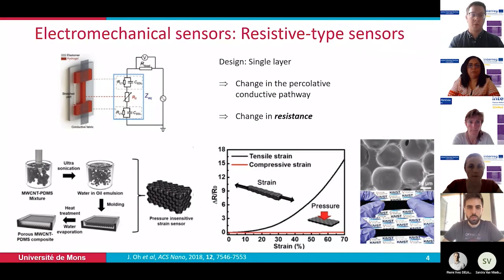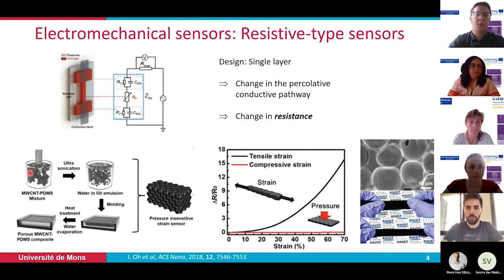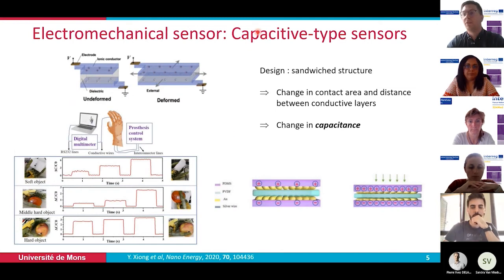As an example, we have here multiwall carbon nanotubes mixed with PDMS, and when you apply a pull on the material, you have a difference in resistance, but the constraint is that when you apply a pressure on this material, you have no response at all. A second type of electromechanical sensor is the capacitive type sensor. There you have a sandwich structure where a dielectric is sandwiched between two ionic conductor layers. When you apply a deformation on the material, you have a change in the contact area and the distance between these two conductive layers.